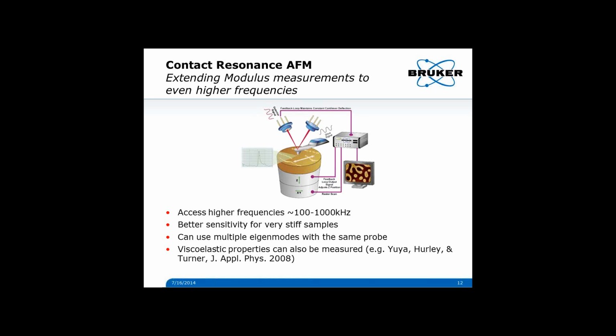The problem with contact resonance for polymers is that it is a contact mode technique, so it suffers from the uncontrolled lateral forces that we talked about earlier between the tip and the sample. Also, the vertical force between the tip and sample is susceptible to variation, because the background deflection, where you're not in contact, can sometimes vary a little bit if there's some variation in room temperature or in electrostatic force between the tip and the sample. That would be a long-range electrostatic force.